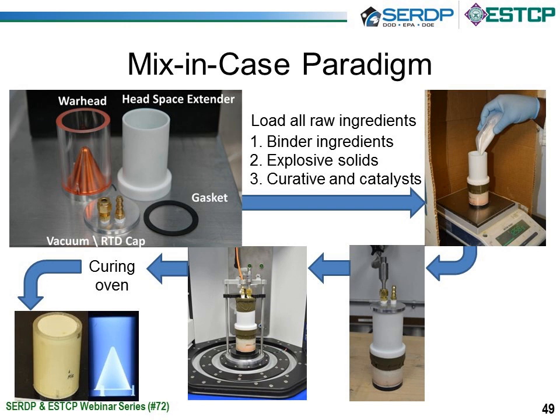The binder ingredients go in first, followed by the explosive solids, followed by the curatives and the catalyst. Everything gets assembled with the vacuum cap with the RTD going down into the material so that we can measure the temperature of the material as we mix, as well as pull a full vacuum on the material so that we can degas it as it's being mixed.